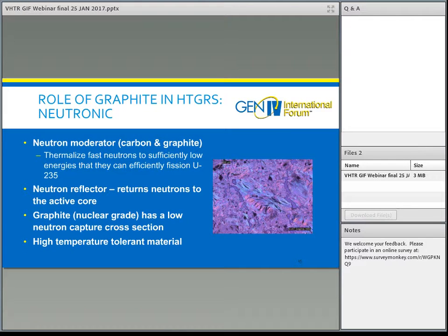So moving from fuel to the next material element, there is the graphite, which plays a key role in high-temperature gas reactors. In the area of neutronics, the graphite serves as your neutron moderator, as I mentioned before. It thermalizes the fast neutrons that come off of a uranium fission event to a lower energy that can efficiently fission with uranium-235, which is the primary fuel of this reactor. It also serves as a neutron reflector to keep the neutrons in the core. It reflects them back in. The key way that occurs is because it does not absorb neutrons; they are reflected back because the graphite has a low neutron capture cross-section.